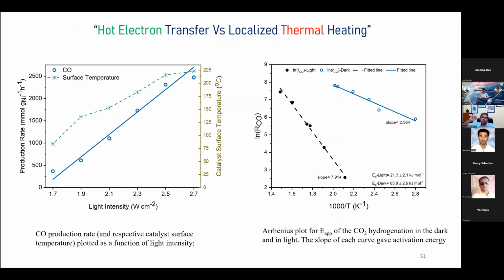If it is really a hot electron mediated reaction, then the kinetics of the reaction should also increase if I'm putting in more photons and generating more electrons. That's what we observe. With increase in the light intensity, there is a linear relationship between the light intensity, number of photons, and the production rate, indicating again that it is a hot electron mediated reaction.